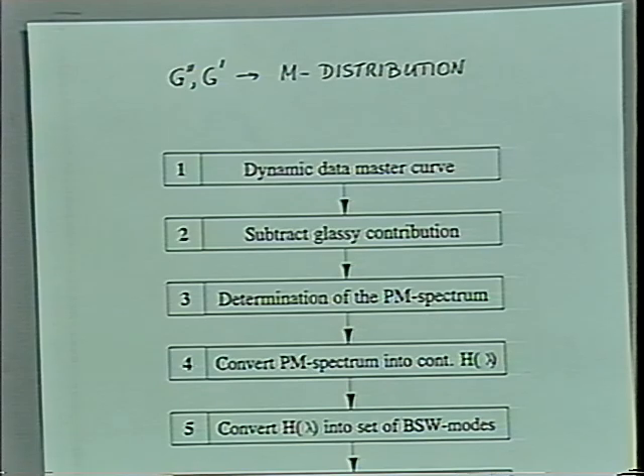There are polymers which you couldn't run through your GPC. Take Teflon, for instance, where you have a hard time finding a solvent, and if you have one, you should operate above 300 degrees C. Now, even your best friend will not give his GPC to you if you want to use it at 300 degrees C. But you can measure G prime, G double prime at high temperatures very easily.